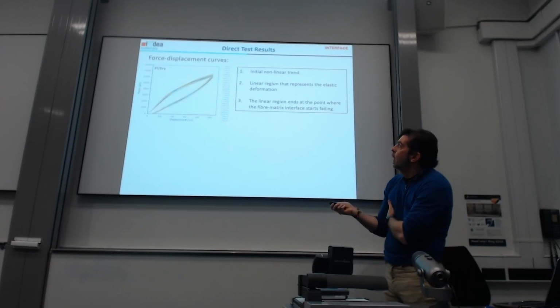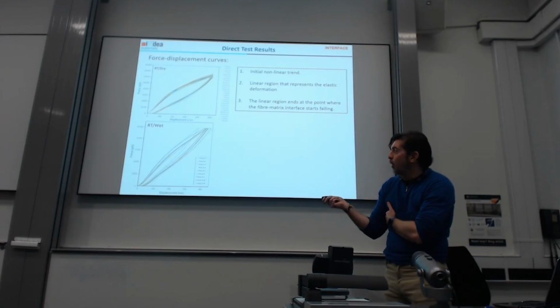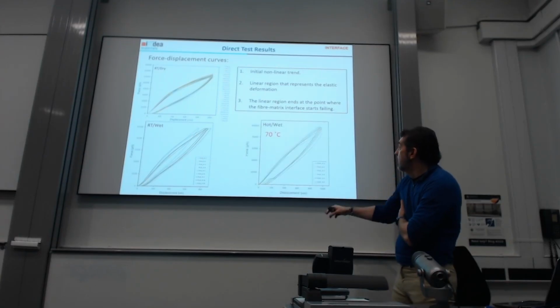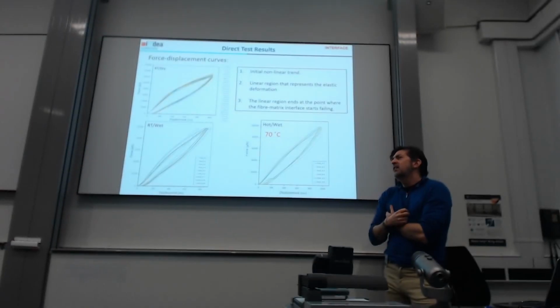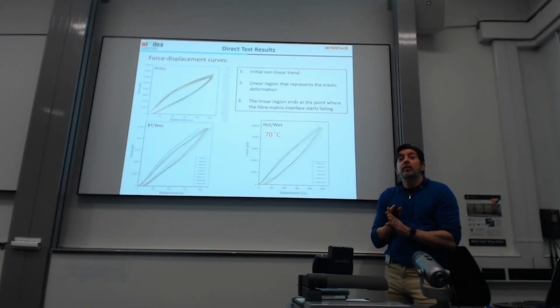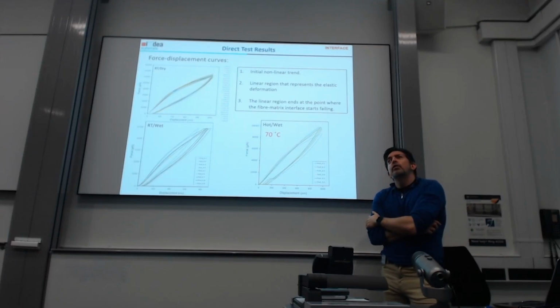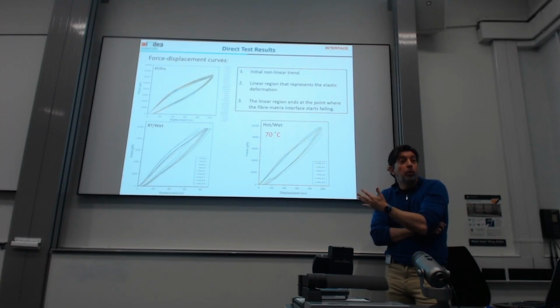This is for the wet sample. It was more difficult to find fibers, so there was less reproducibility. And this is actually the test I did sometimes with 70 or 80 degrees, depending on what the customer wants. We normally do this test for Airbus or Excel. They want this pushing test more and more. This is not part of a research project, but sometimes they say 70 or 80 degrees. I say whatever. Then I do 70 if I can choose.